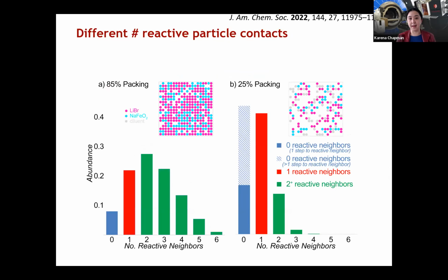Another way of looking at that is we can look at the two different packings and say, well, when we smushed our reagents together, then most of our particles were next to a particle that it could react with. But when we had the lower density packing - this 25% packing case - this is typical of if we just took that powder and put it in a capillary, like preparing a normal powder diffraction sample.